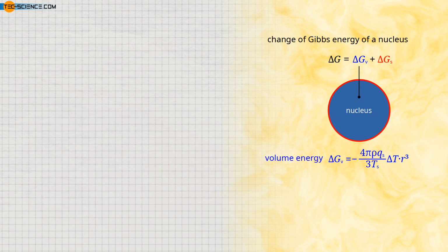In the following, we will take a closer look at the second term, which describes the energy content of the nucleus surface, the surface energy. As already explained, the surface energy must also be taken into account when a nucleus is formed. The second term of the equation, already explained, serves this purpose. This term leads to an increase in the Gibbs energy, since energy has to be supplied to form the solid surface. This term is therefore always positive, regardless of whether the nucleus forms above or below the solidification point due to thermal fluctuations.